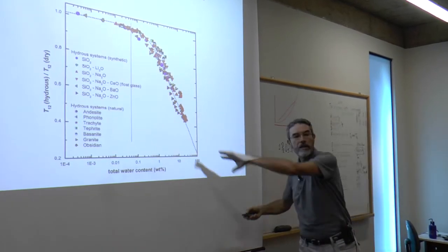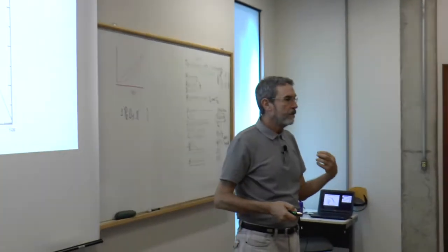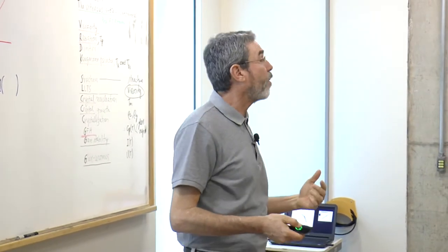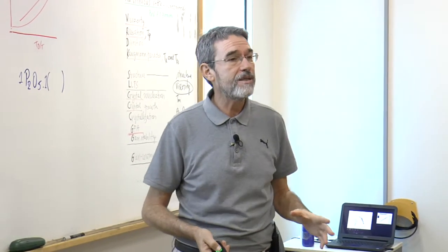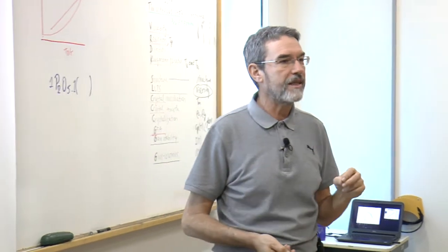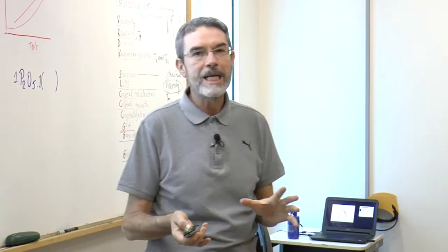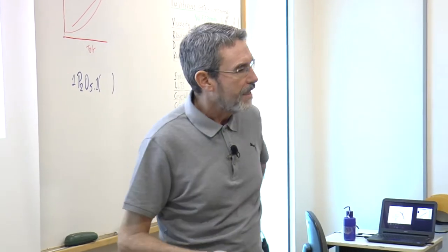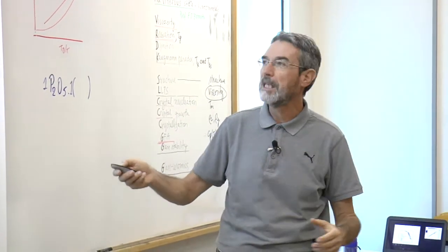So if the viscosity decreases, then the diffusion rates, the relaxation rates, the nucleation rates increase, the crystal growth rates increase, the glass forming ability decreases. It has a strong effect. I think metallic glasses do not suffer from this effect here, but they suffer from another effect. They may oxidize a little bit. When you're trying to produce a metallic glass, certain amounts of oxides are formed which induce complications, but no water as far as I know in metallic melts.